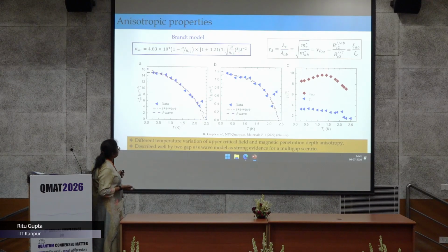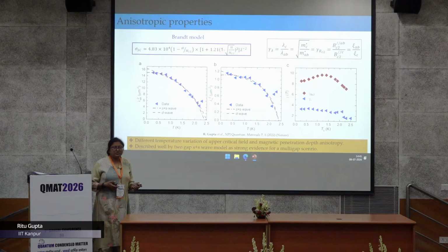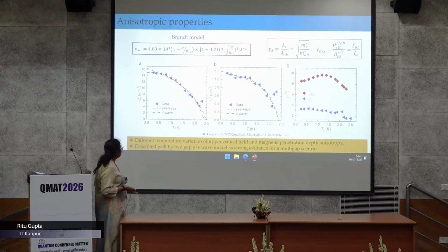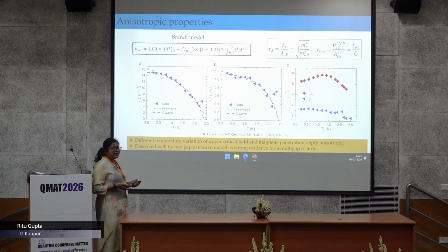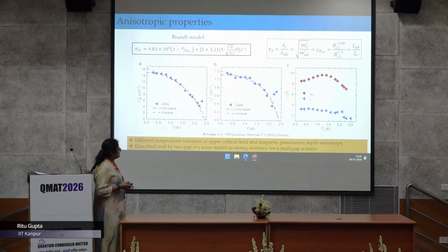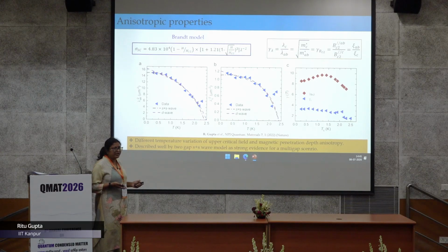These are the parameters which are known from other techniques. So we could calculate the inverse square magnetic penetration depth along the AB plane and along the C axis, and both of them are plotted here. And we tried to fit using different models, and we could fit our data reasonably well with the multi-gap S plus S model, showing the multiband nature of superconductivity, which is further supported by this anisotropy parameter which I plotted here.